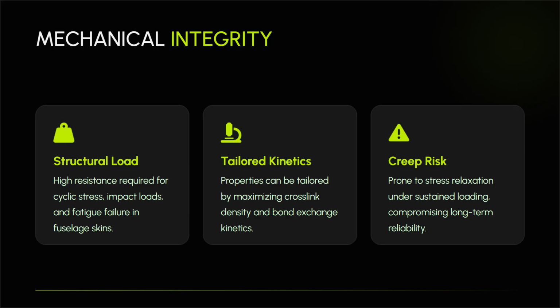Because the covalent bonds within Vitrimers are dynamic, long-term exposure to sustained mechanical loading, especially under stress, can trigger progressive molecular rearrangements. This causes the material to deform over time. For primary load-bearing structures in aviation, even a minute amount of structural deformation is unacceptable, making creep resistance one of the primary challenges that researchers must resolve.